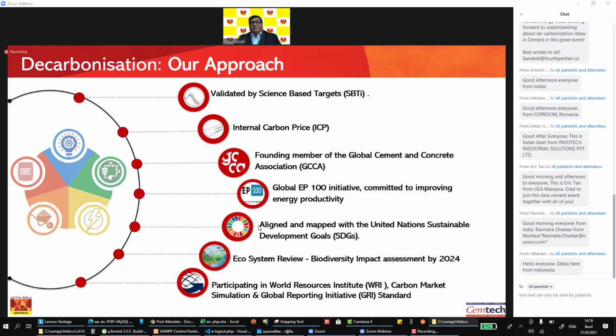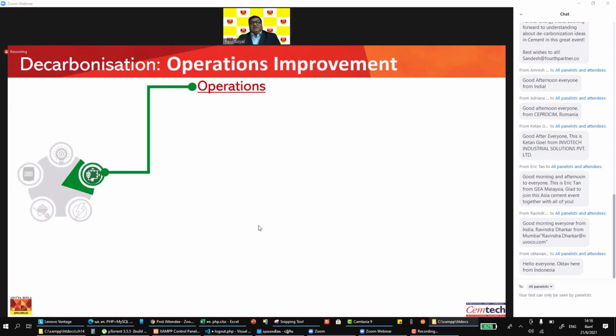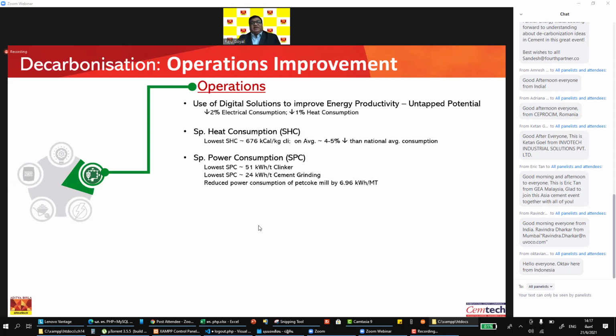Let me talk about our 5-pillar strategy. First, operations improvements, which we are focusing on. In the operations, we are looking for untapped potential by using digital solutions to improve energy efficiency, using AI, ML, soft sensors, and the latest technological developments, which has resulted in about a 2% reduction in energy consumption and a 1% reduction in heat consumption in the past few months and almost a year. In addition, we have achieved our lowest heat consumption, 676 kilocalorie per kg of clinker, which is our average heat consumption as a company,